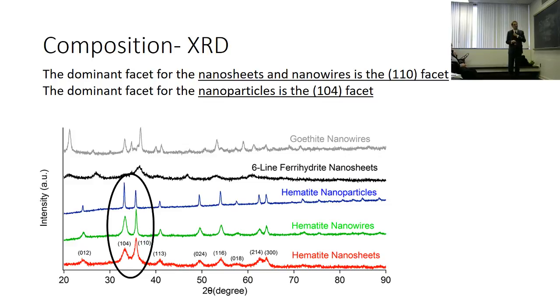And the important part is that all of these peaks are in the same spot. That means it's hematite. But something to notice and keep in mind is that the relative intensity of peaks may say something about what facet of the material is exposed more. It's like you cut an onion in half, but you can do it in different ways, and you see a different shape on the inside. Different facets could have different reactivities.